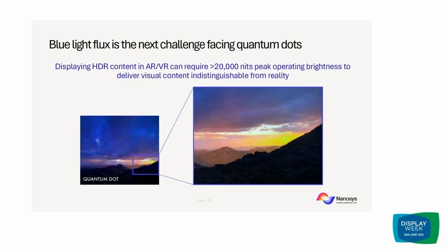So all of those mechanisms that I was describing can happen under photoluminescent excitation, so under low flux applications. But as we're looking forward to future technologies, many people are considering increasing the flux levels of displays. Right now, for QDEF and QDP under typical operating conditions, operating lifetimes are between 30,000 and 100,000 hours. These are top of the end components. They are longer lived than other aspects of the display.